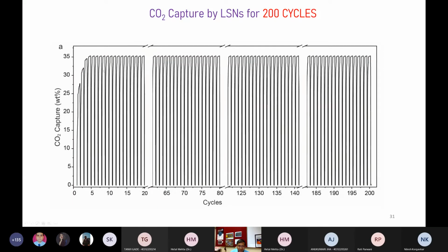And you see it's very stable. It looks very similar, right? But if you zoom in, you will see some changes at the top, but otherwise it looks like a very constant CO2 capture ability of the material, indicating that you can use it not only for 200 cycles but many more, maybe thousands of cycles. So that will make the process sustainable.